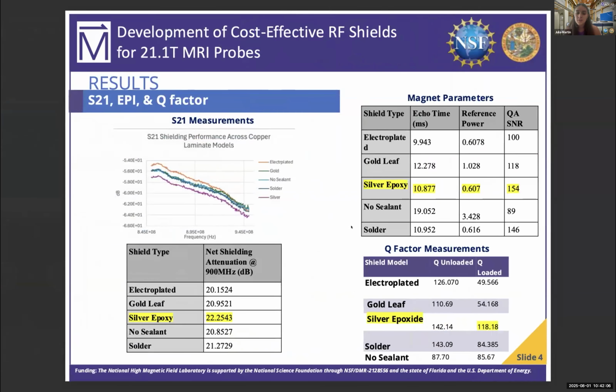Moving on to my results, it is clear that the copper-clad laminate shield joined by silver epoxy performed best in all areas of evaluation. Taking a look at magnet parameters, the only model that did not perform competitively against the electroplated reference was the no sealant model that exhibited a significantly lower QASNR and a high reference power.